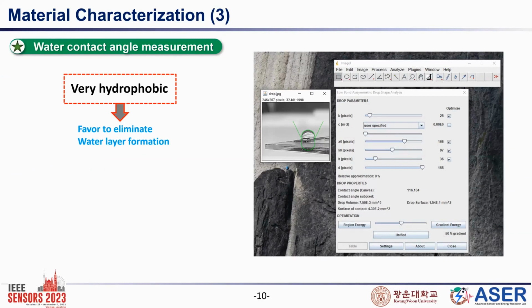And then we have tested the hydrophobicity of our solid contact material, because it is very essential to eliminate the water layer formation in between the interface of the ISM and the solid contact layer. So for our solid contact layer, we have measured the hydrophobicity in terms of water contact angle measurement. We have got a water contact angle of 116 degrees. So it indicates a very good hydrophobic nature of the solid contact material.